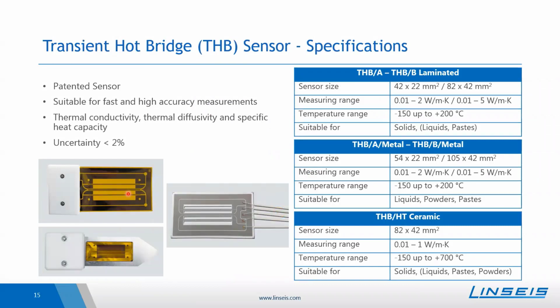So the THB sensor is a patented sensor and is suitable for fast and high accuracy measurements, and can determine the thermal conductivity, diffusivity, and specific heat capacity of solids, liquids, powders, and pastes. For each application, there is its own sensor. The QSS sensor. QSS stands for quasi-steady-state and is suited for samples with a high thermal conductivity, and the sensor has a special layout and uses more or less both, so a transient and also a steady state method. It combines the advantages of both methods to be able to determine high conductive samples in an easy way, so without a complex theory.